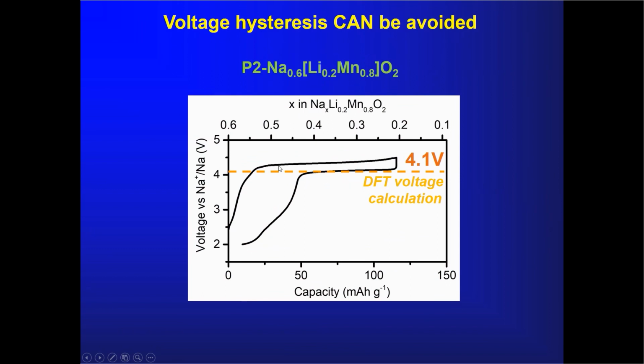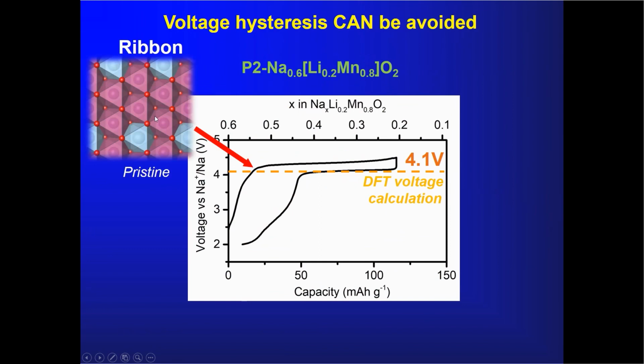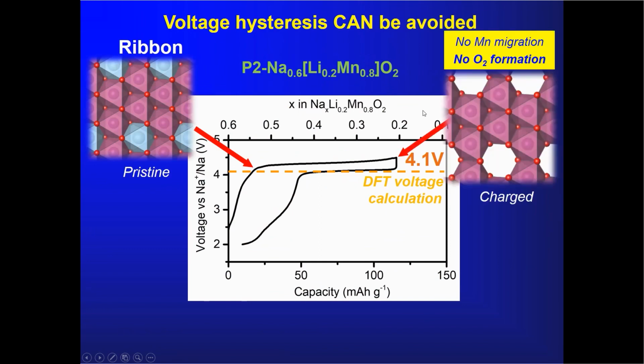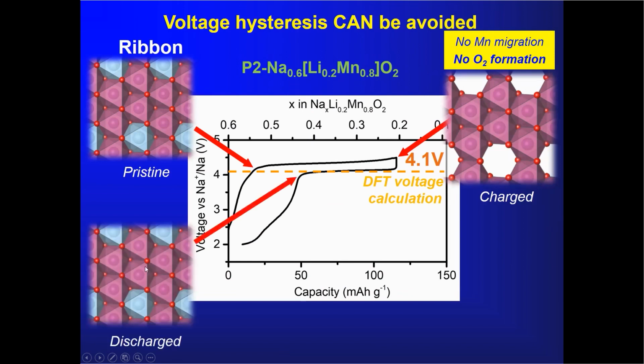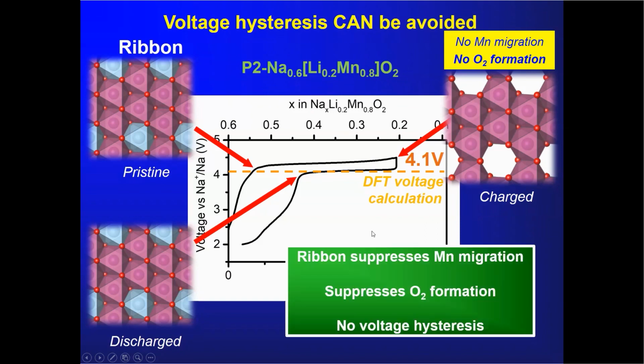And if you carry out DFT on this system, which unsurprisingly, because it has the same structure, you simply remove lithium, you retain the ribbon structure, you discharge again, you put the lithiums back into the same sites. Naturally, you come along pretty much the same voltage curve, and the DFT predicts a voltage in this region for these structural changes. So the point is, you see that the ribbon structure, changing the superstructure of the transition metal layers, the ordering in the transition metal layers, doesn't allow the vacancy clusters to form that you need to permit the dioxygen to form that you would like thermodynamically, but it doesn't allow this to happen. And this suppresses the so-called voltage hysteresis.